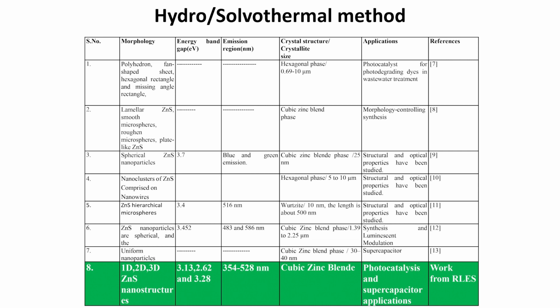Emission region, that is 516 nanometers, and the crystal structure is wurtzite with a 10 nanometer crystallite size and a length of about 500 nanometers. In this structure, the structural and optical properties have been studied. For the uniform nanoparticles, the cubic zinc blende phase has also been obtained, and the crystallite size is of the order of 30 to 40 nanometers. The potential use of this particular nanostructure morphology is in the supercapacitor.